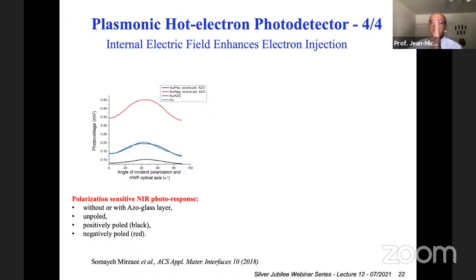If we orient the dipoles towards the layer of gold, we increase significantly the photovoltage, like is a red curve. If we orient the dipoles towards the opposite direction, we decrease the photovoltage. So actually, your photodetector is sensitive to the polarization of the material. So we have a layer of material. It's sensitive to this one.